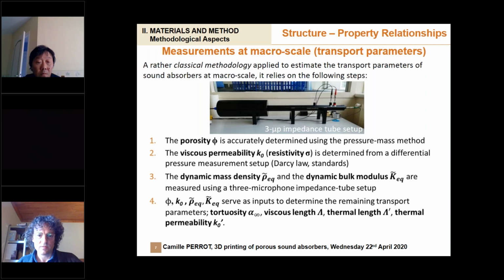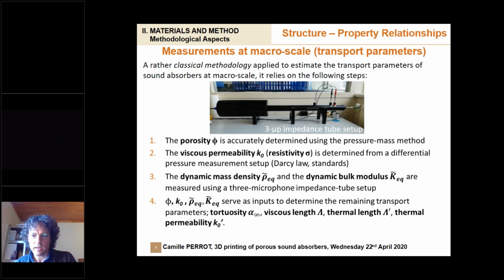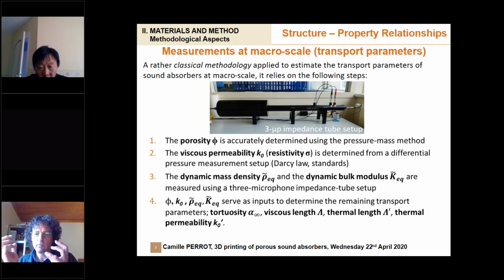But what I would like to say is that minimization of the cost function means that you have several possible solutions at the macro scale, and this means that you will get a proper description of your sound absorbing behavior. But because those macroscopic parameters are all linked together, this does not mean that it's strictly related to microstructure. You have a description at macro scale, but because you have no unique solution, if you minimize a cost function, it could mean that the sets you obtained are not directly related to the microstructure.